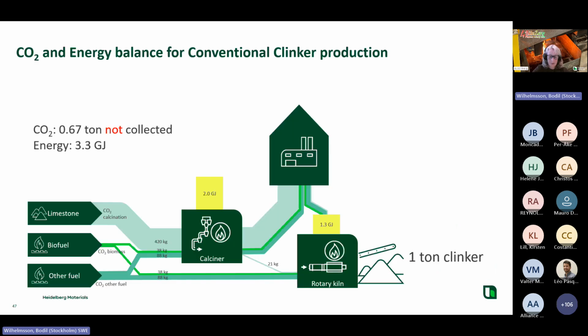If we look at a typical scheme of what happens when producing 1 ton of clinker, we need limestone, we need fuel. Many plants use biofuel and other fuels, of course, and then we calcine it and we put it in a rotary kiln. Totally in the flue gases, we have 0.67 tons of CO2. And we need energy of 3.3 gigajoule. And how to handle this? It's not enough to remove the fuels, because then we still have a lot of CO2. 2/3 of the CO2 is still there, as I showed.